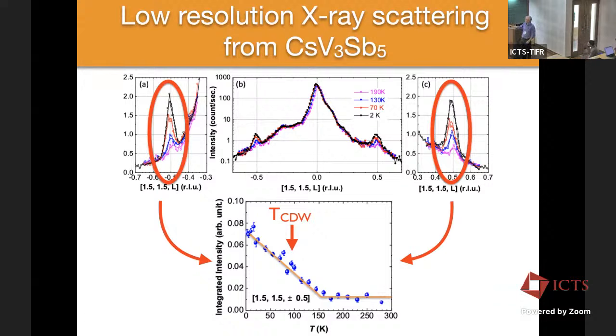So this plot here is coming from this data, and you can see that where this goes to zero, that's where the peak goes away. The intensity at that point does not go away, and that's because you're sitting on this streak of scattering, which is at the half-half positions within the Kagome plane, and if you go perpendicular to the Kagome plane, you've got basically a rod of scattering, which is temperature independent. And so when this scattering does go away, it's still sitting on that streak of scattering. So you're not actually at background.